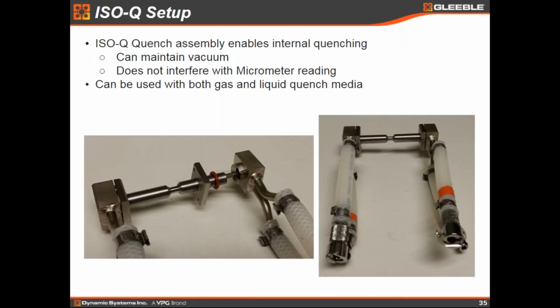I'll briefly touch on IsoQ setup. Brian did a good job of already talking about most of this. As he said, it enables internal quenching, which is difficult to do otherwise, really. You can do external quenching with dilatometry, but that leads to more complications. The benefits of internal quenching are obviously that you can maintain vacuum. There's not a concern in that regard. And if using the micrometer, it's not going to interfere with the micrometer reading at all. Blasting water around, maybe potentially moving your thermocouple, everything else might cause some problems otherwise. So internal quenching is very useful for that. And as I believe he mentioned, it can be used for gas or liquid quench media. Both of them work just fine with that.